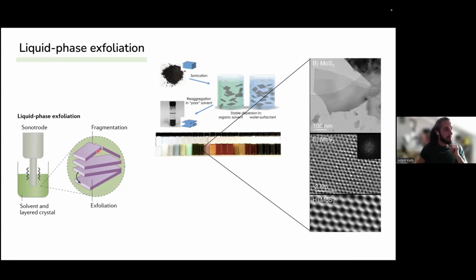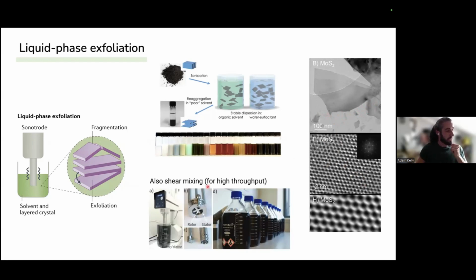Now, this is quite a mechanically aggressive method, but when you look inside using TEM, what we find are pristine basal planes. And generally, the defects associated with these nanosheets are associated with the edges themselves. This technique is also scalable. You can use shear mixing here to generate liter scale quantities. In a similar method, the material is pulled in through a rotor, and the shear effects caused by pulling the material in through here and pushing it out cause delamination.